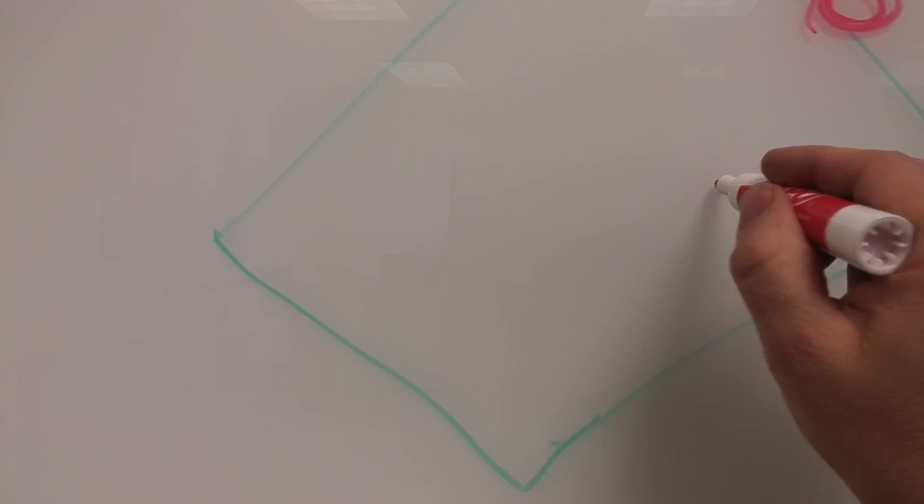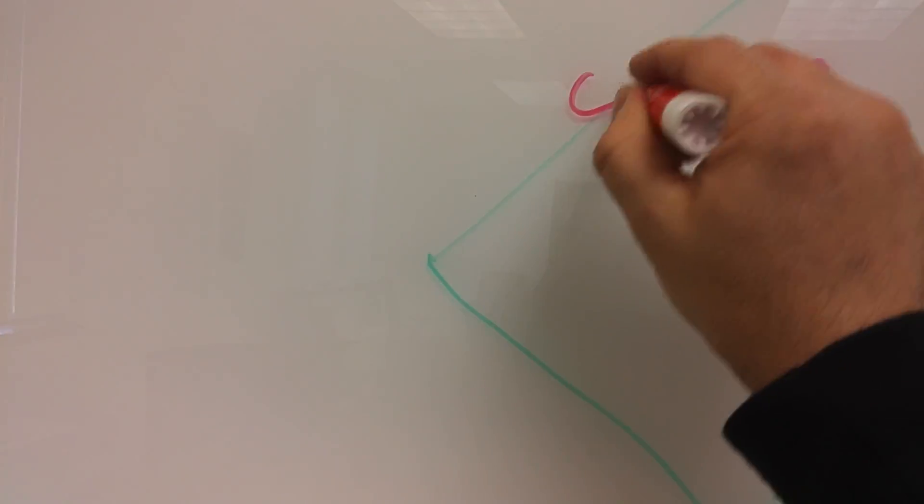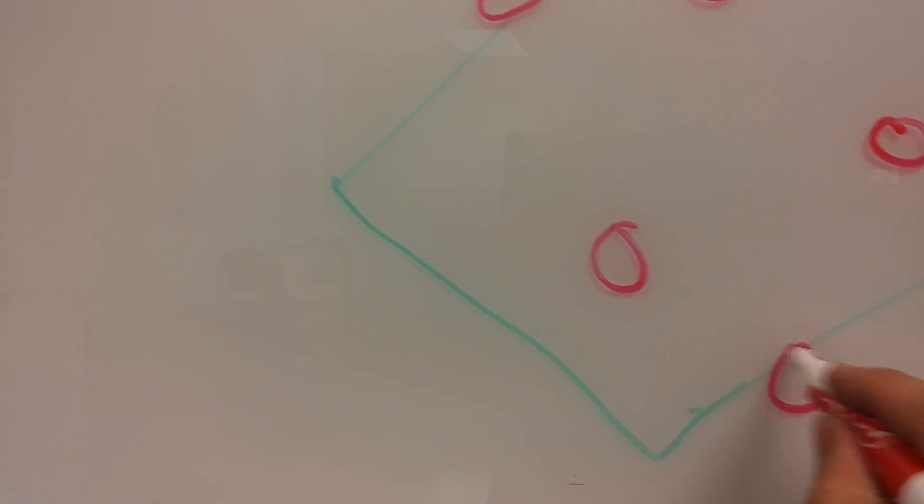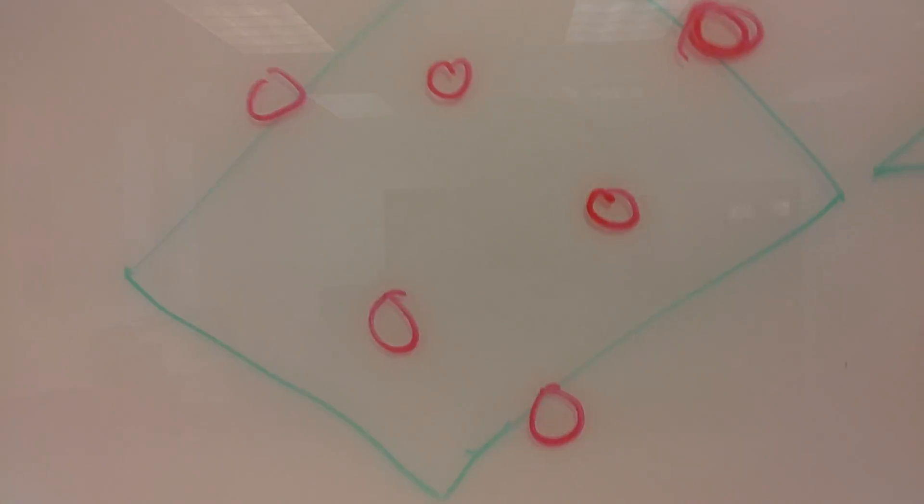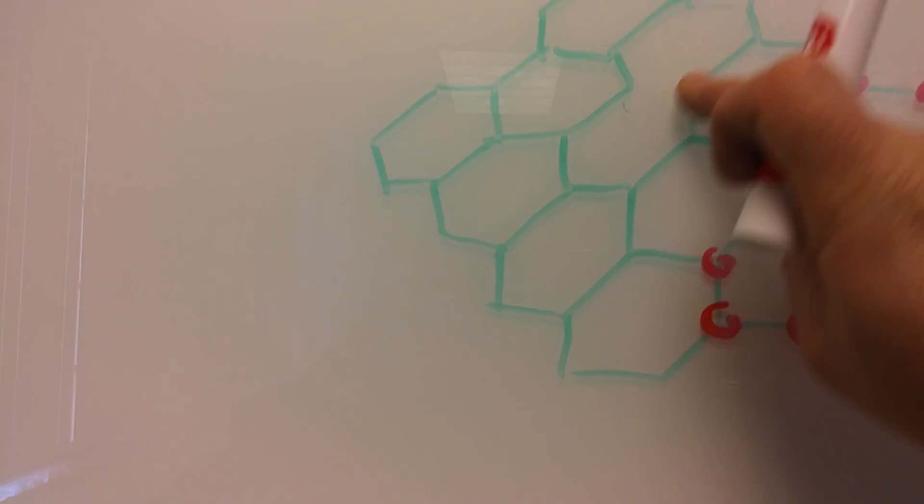Here's why: because in actuality, when you reduce it, when you put graphene in, or graphite in the acid and make graphene oxide, this is where the function groups actually happen all over the place across the sheet. Each time there's a function group, you're taking away this little lattice shape. You can see that lattice shape, you're taking away that lattice shape. Let's add some more here just because.